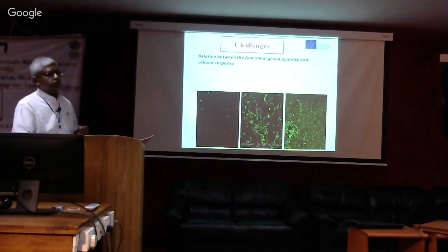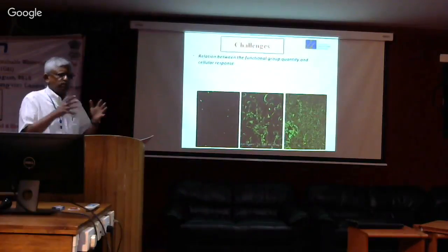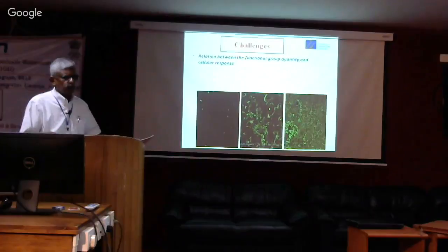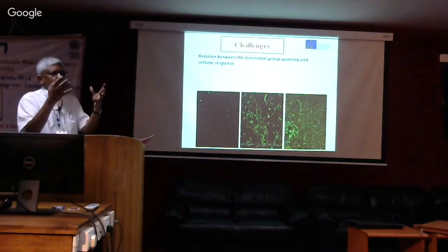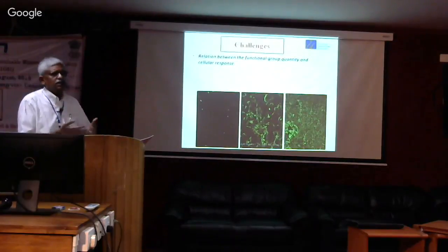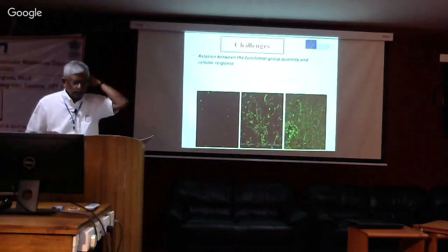The other way is you use chlorosulfonic acid, and chlorosulfonic acid is very, very aggressive, and it needs a lot of safety protocols and so forth. When we would do that, the polymer would disintegrate. And of course, if the fiber disintegrates, then there's nothing really left for you to work with. All right.